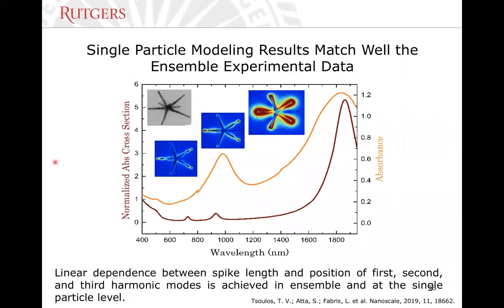And a very interesting aspect of these nanoparticles is that we were first able to model them, as you can see here. This was a model that we developed without knowing a priori if we would ever be able to make this nanoparticle. What we found in this model is that there are 3 resonant bands associated with the spikes that we can observe. We call them first, second, and third harmonic. You can also call them multipolar modes. We decided to call them this way because we found a resemblance in antenna theory, in the separation of the resonances depending on the morphology and properties of the antenna.